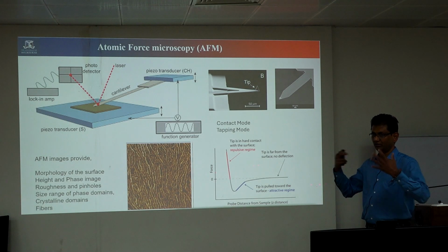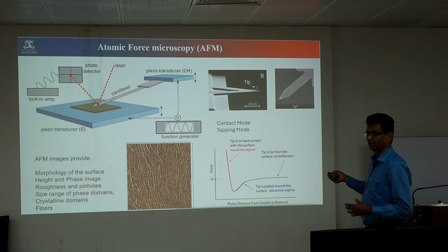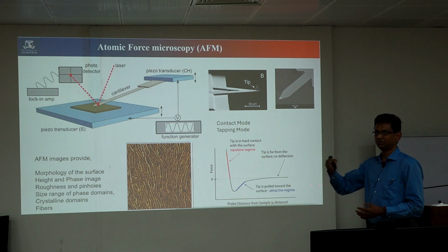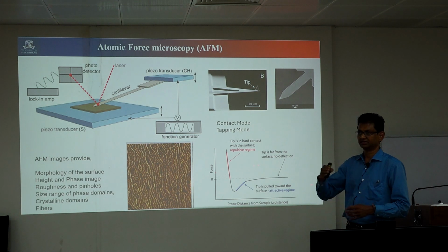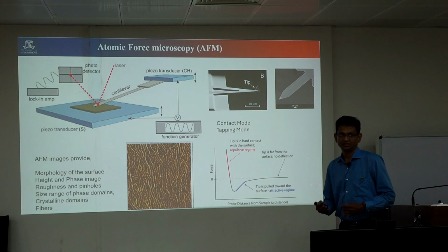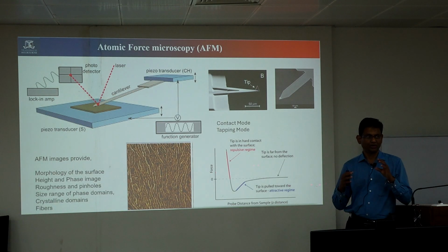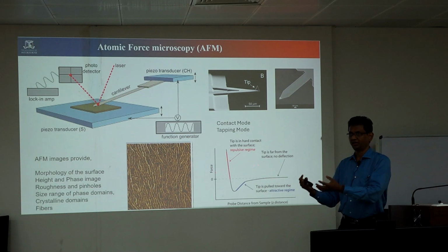That one, we need to have some idea about. If the tip is already broken or not there, you don't see the feature size. You don't see the right features, the nanoscale features. It's always like a very plain surface. It will be misleading. So you need some working knowledge of how the instrument works. Then only can we get the required information from the data.